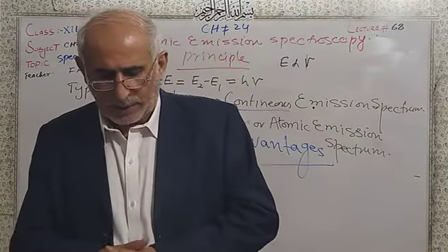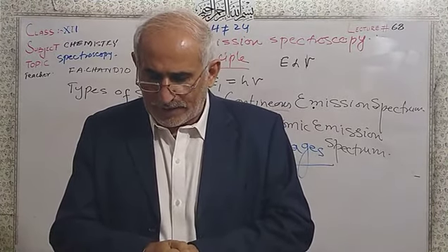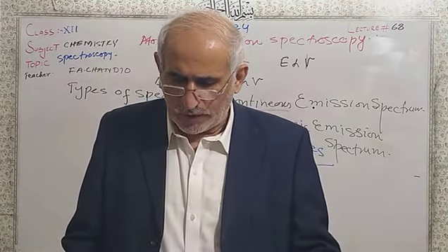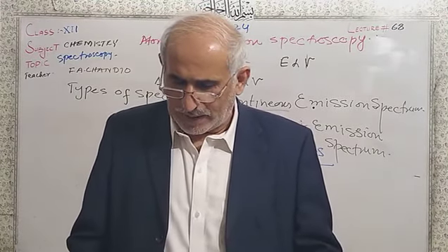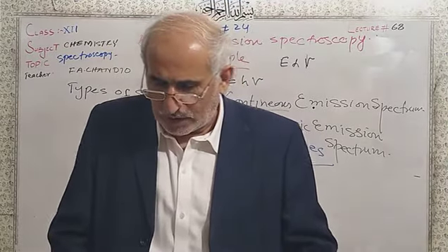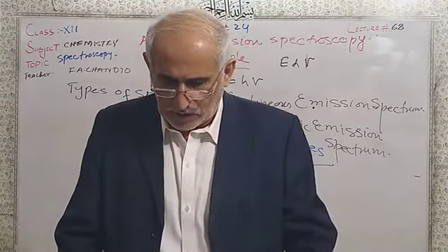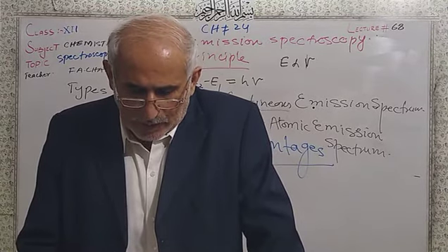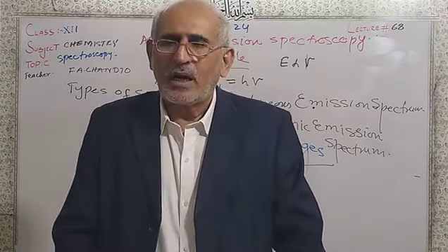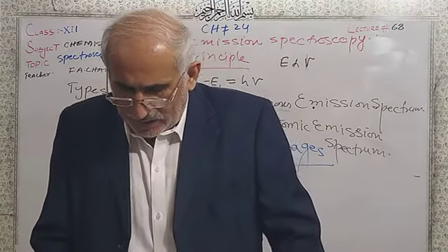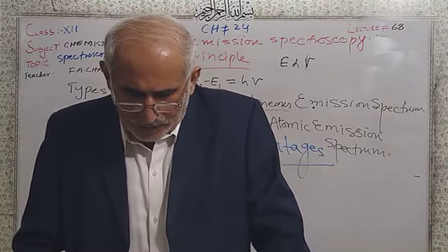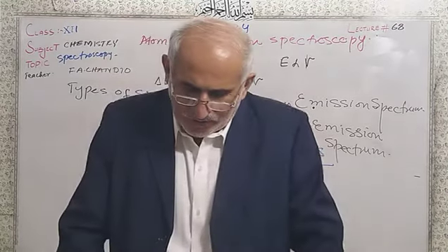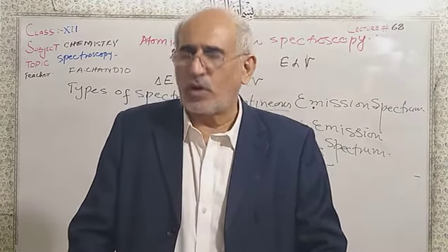Applications, I told you, emission spectroscopy has been employed to determine the impurities in nickel, manganese, chromium, silicon, aluminum, magnesium, silica, tin, cobalt, vanadium, lead, bismuth, phosphorus, molybdenum, iron, even steel in metallurgical processes. You can use alloys also, zinc, copper, lead, aluminum, magnesium, tin can be analyzed. Lubricating oils have been analyzed because they contain metals like nickel, iron, chromium, manganese, etc. Concentration of metal in the liquid lubricating oils has increased during the course. It indicates excessive wear and tear, a need for engine overhaul.